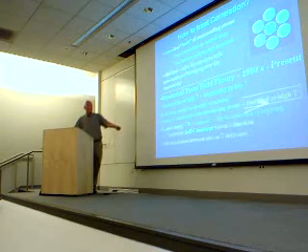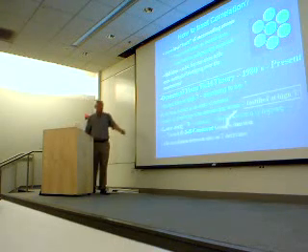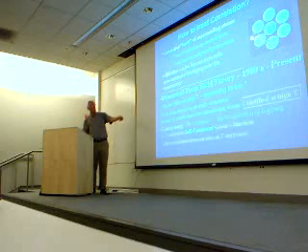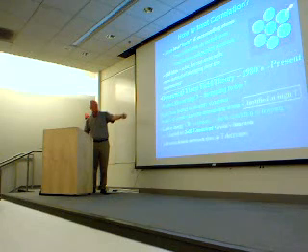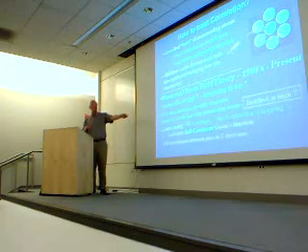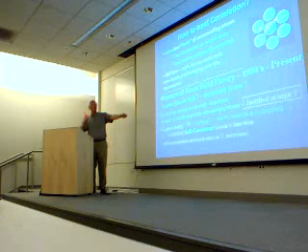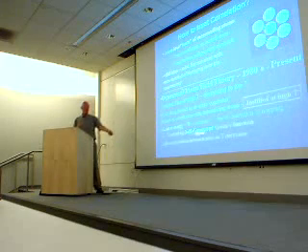That's down here. The thing that I didn't write down in any equations, but is the key thing to think about, is that the one electron Green's function describes the ability for an electron to hop onto or off this site. If we look at the Green's function of this site, it's coupled to the bath around it, and the one electron Green's function is telling you how this atom is in equilibrium with its neighbors.